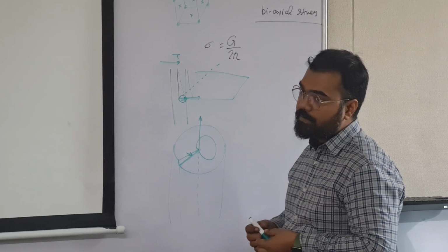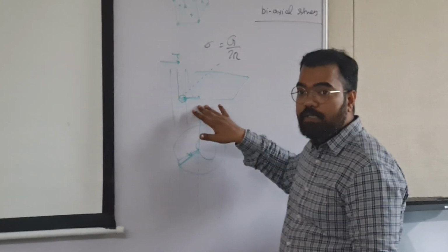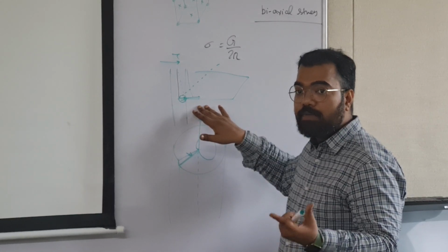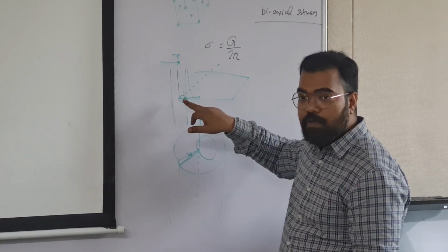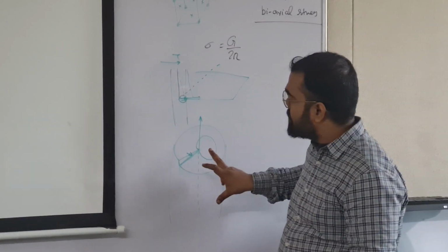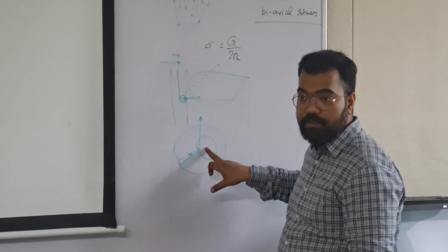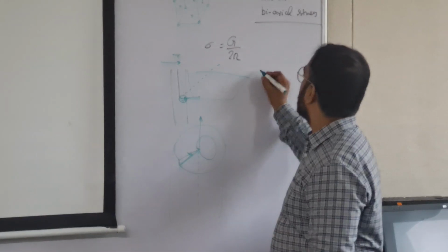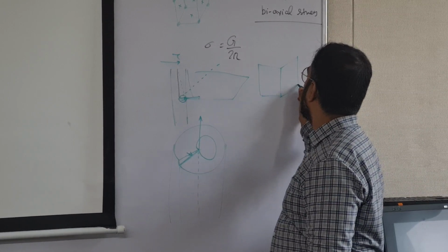And second thing is that edge dislocation has both stress fields of normal stress, so hydrostatic stress, as well as shear stress components. The stress environment which it creates causes both shearing and hydrostatic stress, whereas this one will not cause hydrostatic stress, it will only cause shear stress. And then you can imagine or try to make the octahedral voids which will be forming in an FCC.